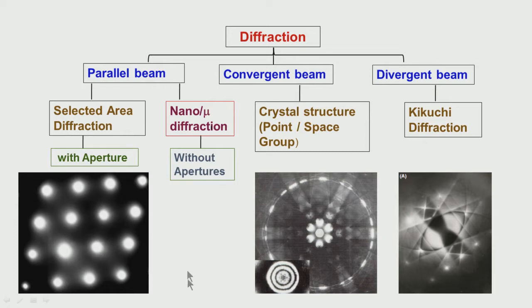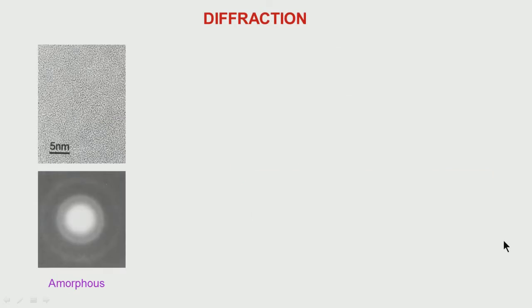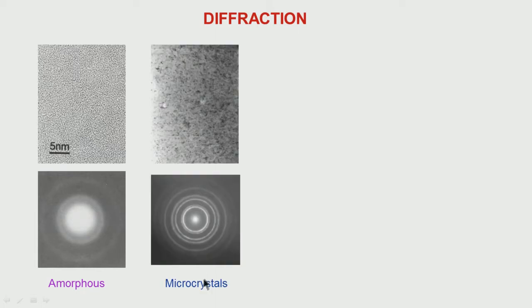To determine all this quantitative information, we could use Kikuchi diffraction. This also will be talked about in a separate class. In a diffraction pattern, from an amorphous region we get a ring pattern, and if the thickness is the same, we get a uniform contrast, there is no variation. And in microcrystals, we can get a ring pattern, a diffraction pattern.